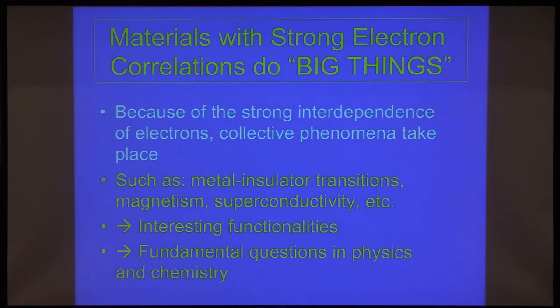So when you say localized, you mean on the scale of the interatomic spacing? You know, I just mean that the overlap of two neighboring wave functions is relatively small. So just to be more quantitative, the transfer integral that you would estimate by the overlap of two neighboring orbitals is comparable to the on-site screened Coulomb interaction. They both are typically on the scale of a few eV, you know. While if you take silicon, right, you're going to have bandwidths that are large, and this on-site screened interaction would be a much smaller scale than that. So that's the general concept.